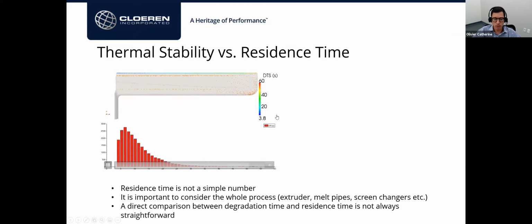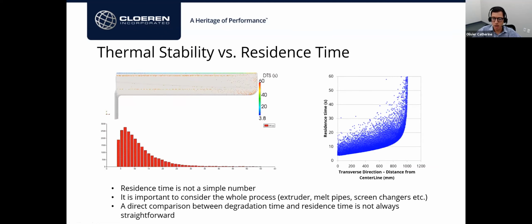And you can see here, based on these flow simulations and particle tracing analysis, this is the envelope of residence time as a function of the position and width of the die. So particles coming out from the center line at 0 to the ends of the die at over 1,000 millimeter, for this one application. You can see the envelope has this type of asymptotic behavior.